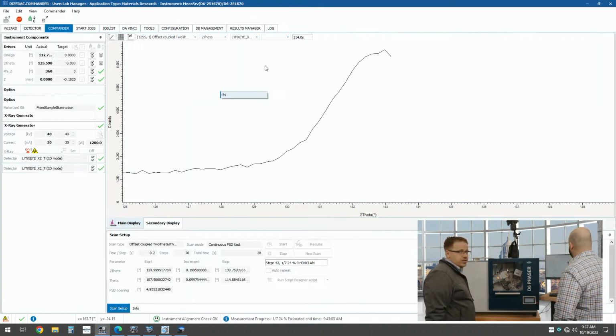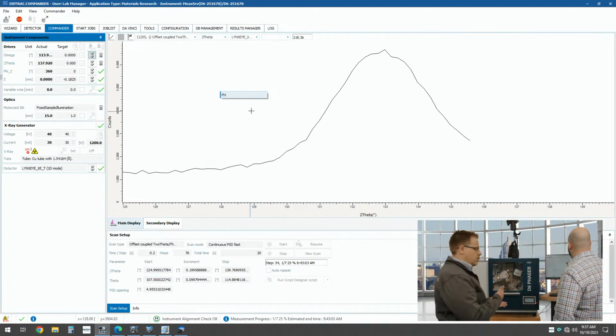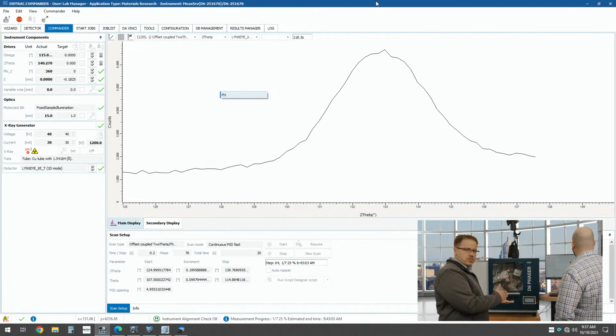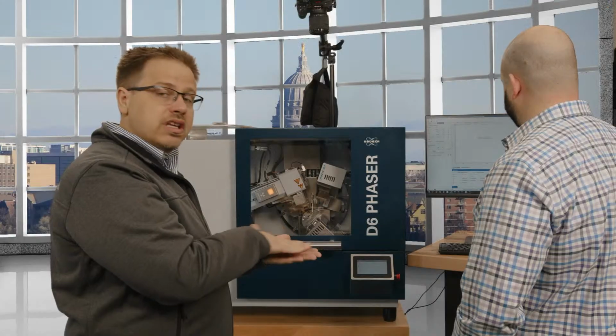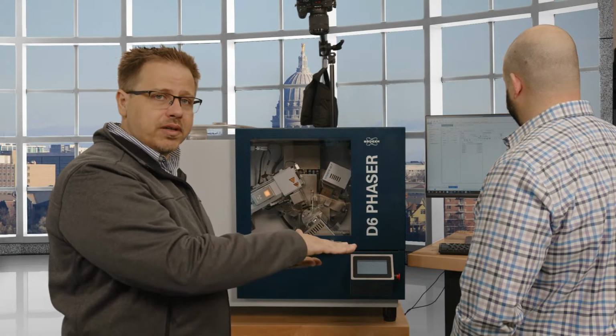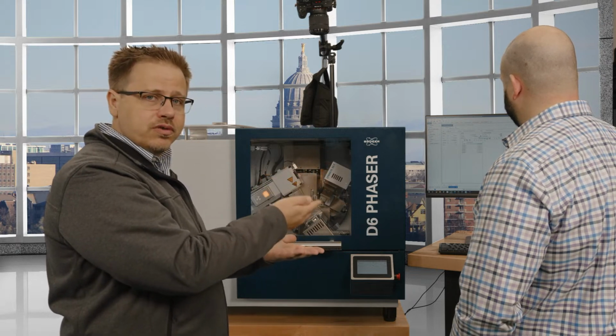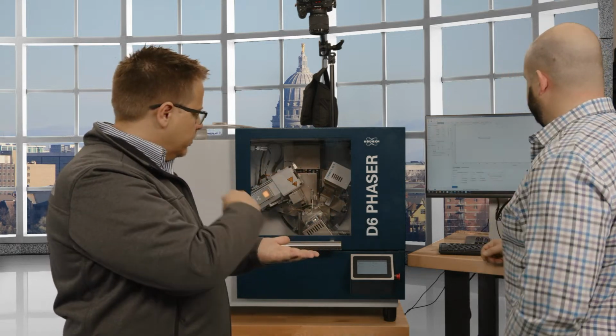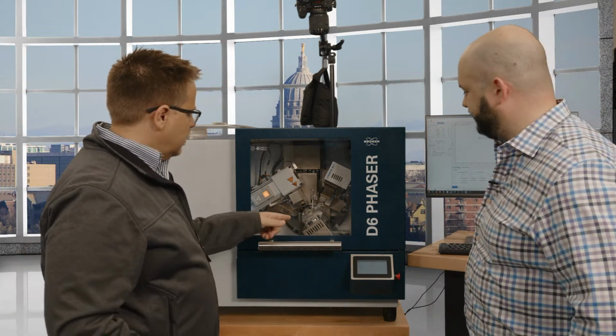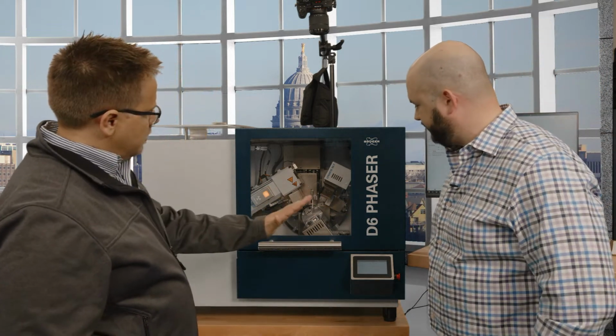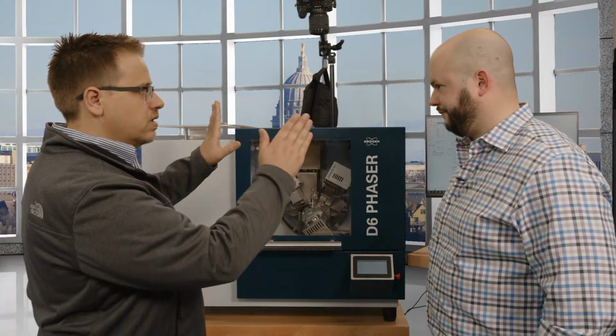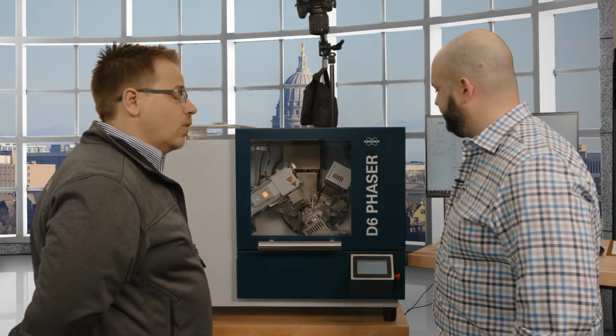All right. So in X-ray diffraction, what we want to do is measure the lattice parameter that's pointing out of the sample, and then we want to measure it in the plane of the sample, but we can't get there directly. So what we do instead is we measure several tilts. And then from those tilts, we can extrapolate the stress itself. So you can see here the geometry that it's using is that the sample's tilted, and then it's doing a scan. Yep. And it's using a 1D mode this time.